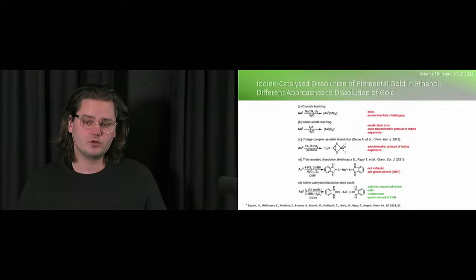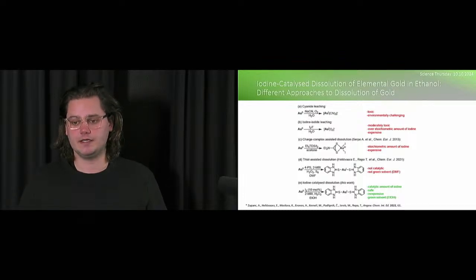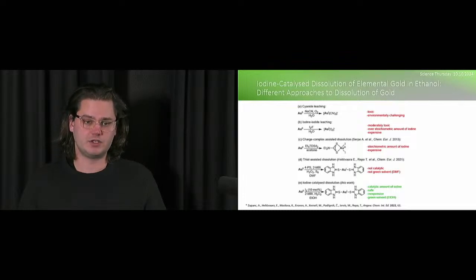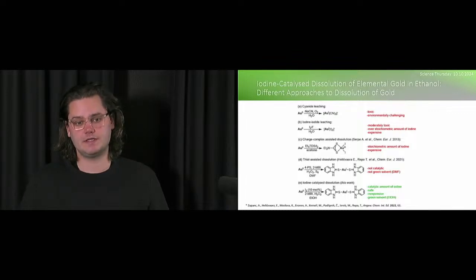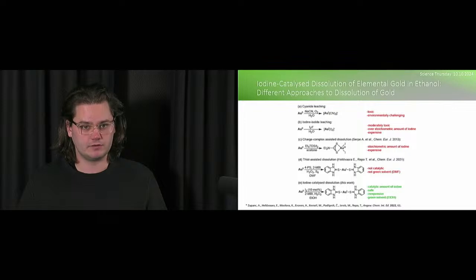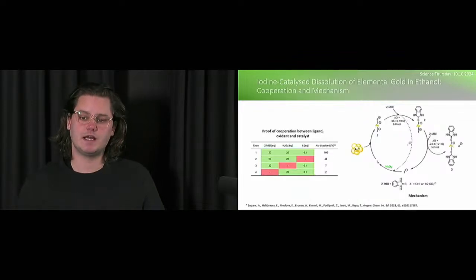So we could also do it by stoichiometric amount of iodine by applying the correct ligands. So what we tried to design was that we would dissolve gold by using just a catalytic amount of iodine, and we would substitute this iodine in the reaction mixture with something cheaper and safer. So what we did was we designed this